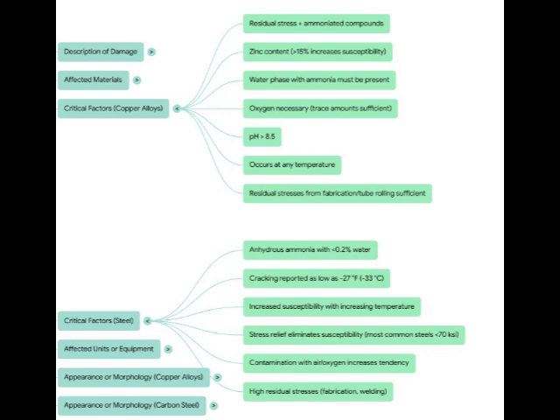Here's where it gets really interesting, because you said the conditions are almost opposite. Exactly. It's this kind of weird paradox. Carbon steel thrives, or rather, fails, under the anhydrous threat. The absolute critical factor here is anhydrous ammonia. That means ammonia with less than 0.2% water. That 0.2% number, that's like the magic threshold. 0.2%, tiny. Tiny. If you can keep the water content reliably above that level, you generally inhibit the cracking, but drop below it and the steel becomes vulnerable.